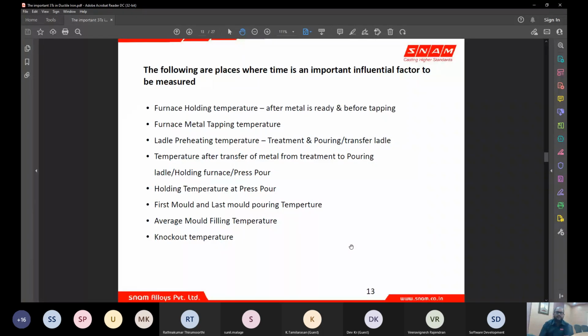Say, for example, a ductile iron's melting point is 1150 degrees Celsius and you hold that metal at about 1520, 1530, which is the tapping temperature of the liquid metal. So you've got a superheat of almost 370 degrees Celsius. And if you hold the liquid metal for a longer time at 370 degrees Celsius extra, you will start losing the nucleation available, because nuclei tend to form only below the liquidus temperature, that means the melting point of the alloy. So you are keeping a very high temperature above nuclei formation, and you start destroying the nuclei when you hold at a very high temperature.